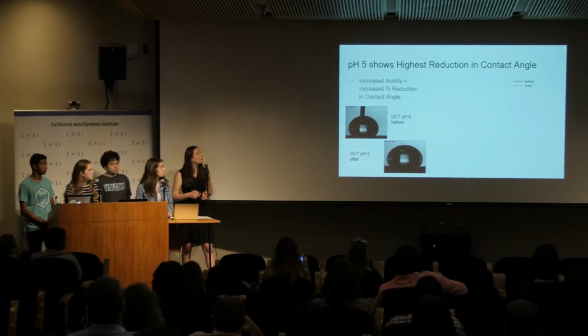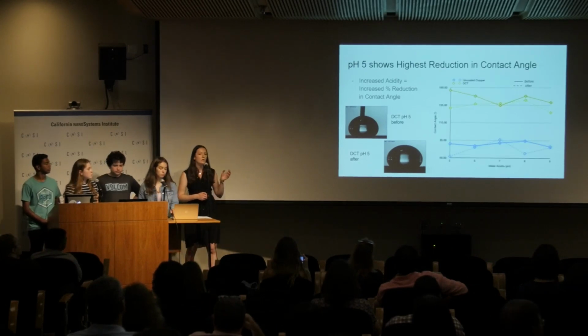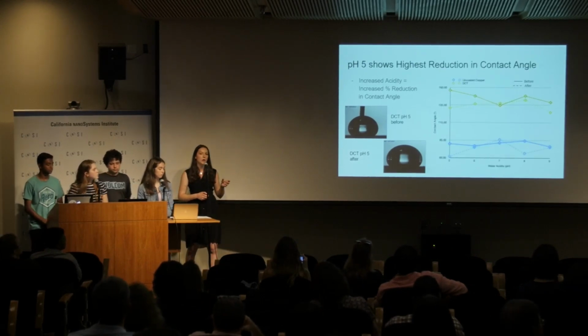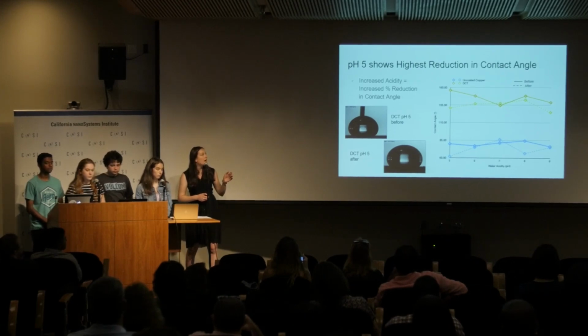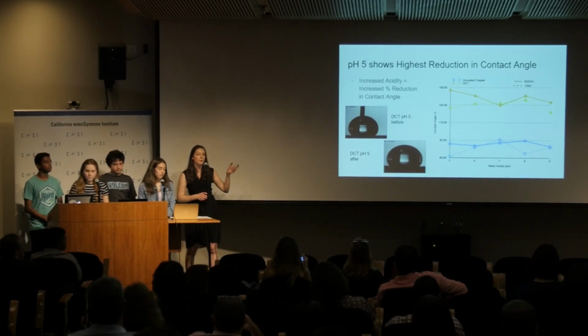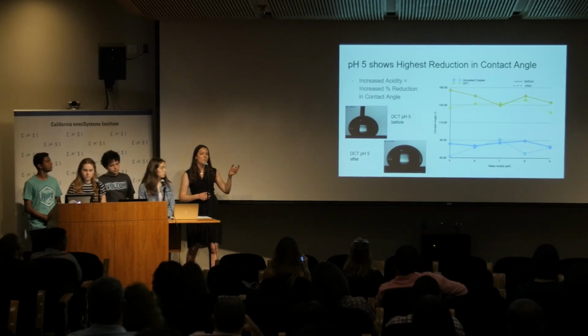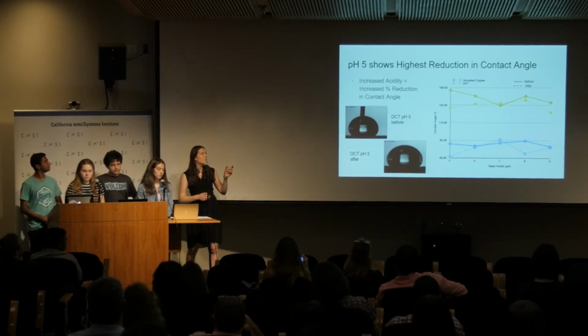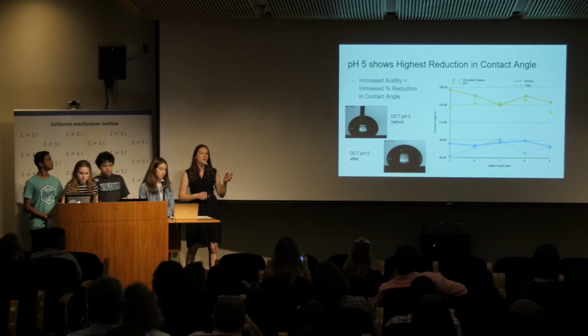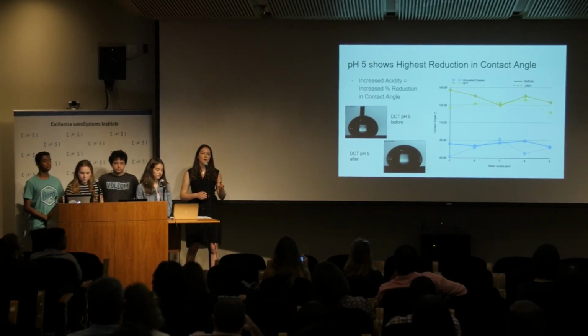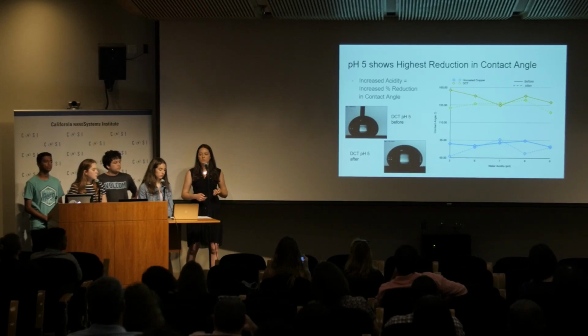And when we zoom in to look at only DCT and uncoated copper, so the best and the control, we can clearly see that there is a drop in contact angle at pH 5, but also that at pH 7, this is where there's the least change, and that might be caused by the fact that it's just water and there's no acid or base in the solution.